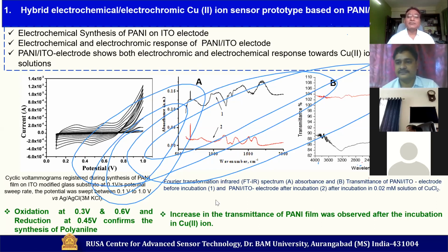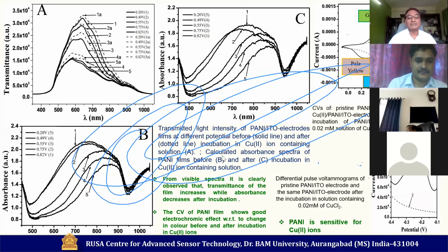Now you can see here, this is the CV which we recorded during synthesis. An oxidation peak at 0.3 and 0.6 volt and reduction at 0.45 confirms that we end up with polyaniline. Then we incubated it in copper ion. You can see this is the FTIR before and after incubation. If you look at this FTIR, absorbance as well as transmittance, you will see a substantial increase in transmittance after incubation with copper ion. This is what we were expecting, and we got the results as well.